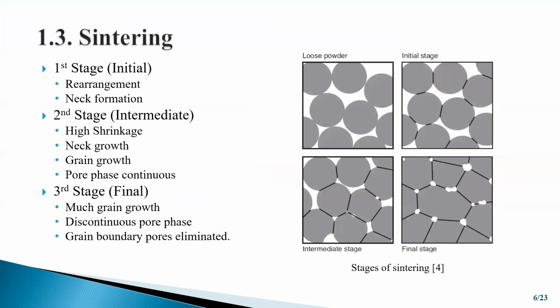Another important parameter affecting the performance of the electrolyte is the sintering process. The sintering temperature and duration directly change the density and ionic conductivity of the electrolyte. Sintering is often thought of in stages. The initial stage involves rearrangement of the particles and initial neck formation at the contact points between particles. The second stage is called the intermediate stage. The neck size grows, porosity decreases, and the centers of the particles move closer together. This results in shrinkage. Grain boundaries begin to move, and one particle begins to grow while the adjacent grain is consumed.